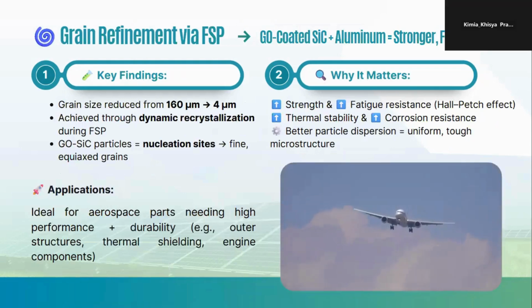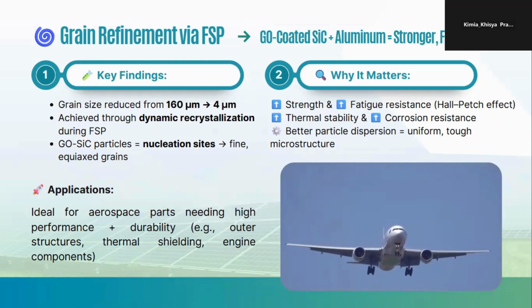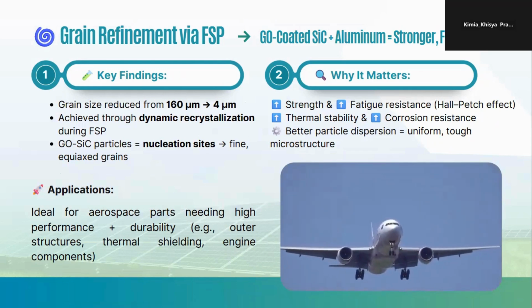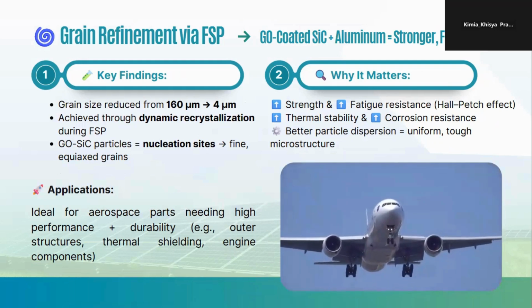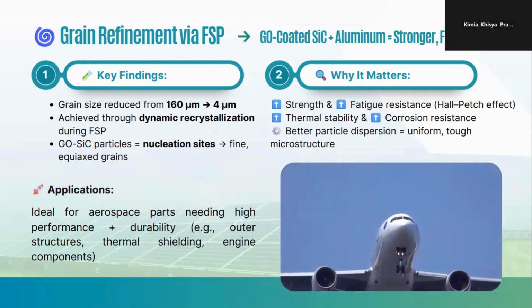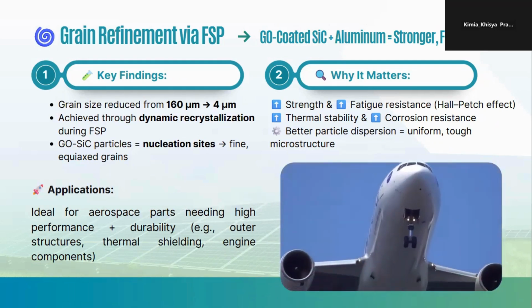Next one, we use graphene oxide and silicon carbide because it refines the grain via FSP. The grain size reduced from 160 to 4 through dynamic recrystallization during FSP. Graphene oxide and silicon carbide enhance nucleation sites. It is fine